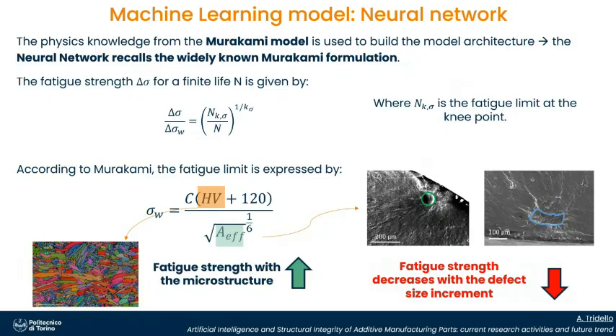And now I show how we embedded this physical knowledge. Okay, this is the widely known Murakami formulation. If we talk about additive, everyone knows it. Okay, and this formulation can be rearranged and it can be shown that the fatigue response is proportional to the microstructure, the Vickers hardness, and is inversely proportional to the defect size. Okay. And this information is elegantly condensed in this very beautiful formula. So we use this as a reference.